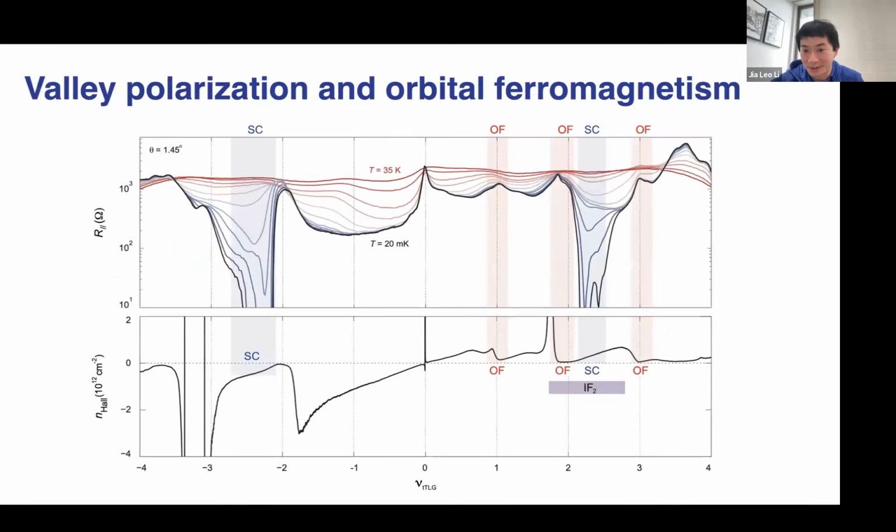Right. So in twisted trilayer graphene, at d equals 0 or close to d equals 0, twofold rotational symmetry or inversion is preserved. And the valley polarization breaks C2, breaks T, but it doesn't break C2T, right? You need something else. You need to break C2T in order to have the magnetic order, in order for valley polarization to couple to external magnetic field.